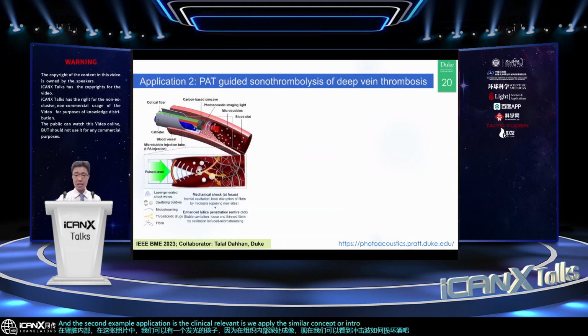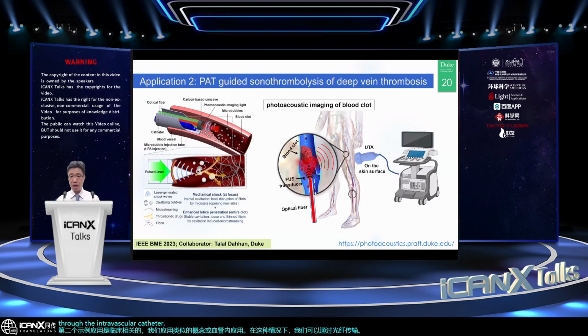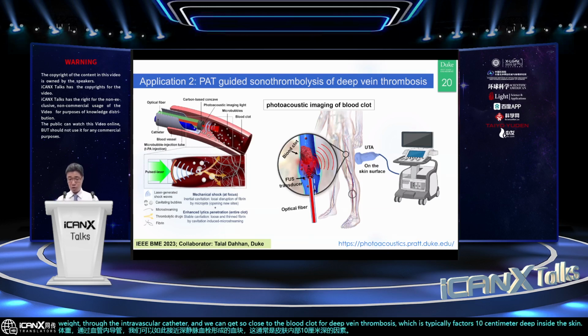In this case, we can deliver light through optic fiber through the intravascular catheter, and we can get so close to the blood clot for deep vein thrombosis, which is typically 5 to 10 centimeters deep under the skin surface. And it's not available for photoacoustic imaging traditionally. So in this case, we can get so close to the blood clot while the ultrasound signal is still detected outside the tissue, and we can provide real-time treatment guidance for the clot.